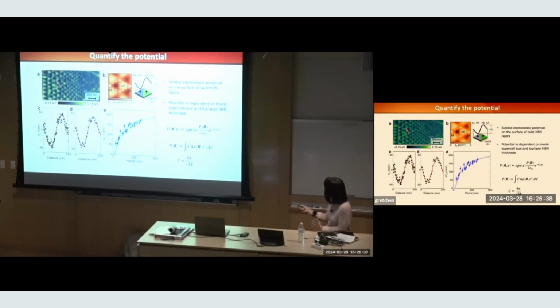The idea is very simple. It's actually classical electromagnetism. You have that charge redistribution. You can calculate a polarization based on the integral of the charge redistribution with z, that's the dipole definition, charge and the separation, right? And then you calculate the potential, and you have an exponential function here. Z is the distance to the interface. So you do want to get close to the interface, but what is this G? The G has some constant over B, where B is the supercell size.